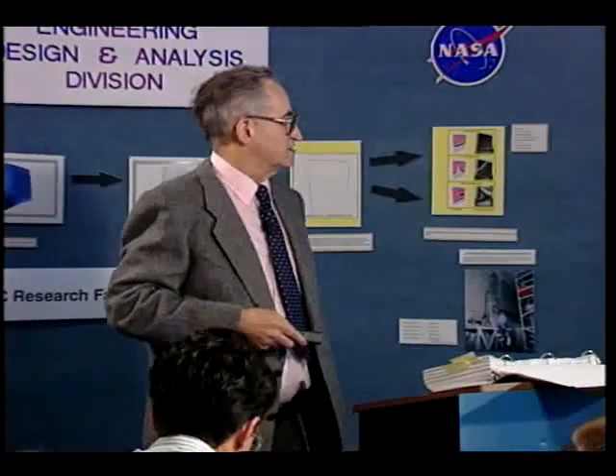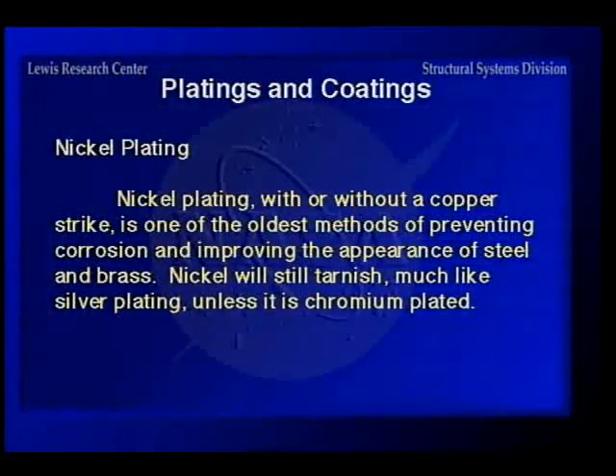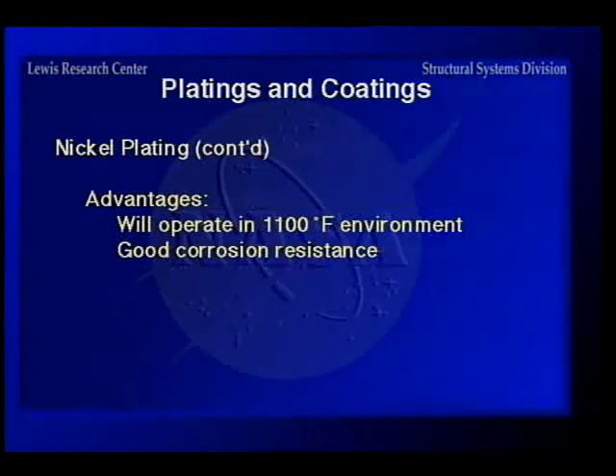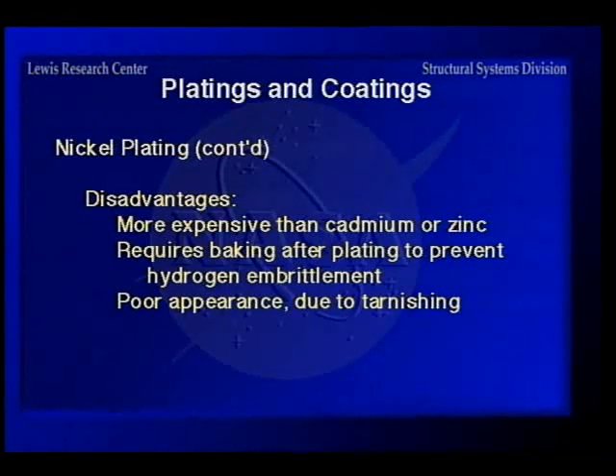Now, nickel plating. Nickel, with or without a copper strike, is one of the oldest methods of preventing corrosion and improving the appearance of steel and brass, but it'll tarnish unless it's chromium plated. But it has a fairly high allowable temperature and good corrosion resistance. The disadvantage, it's more expensive than cadmium or zinc. It requires baking after plating to prevent hydrogen embrittlement, and it doesn't look too good when it starts tarnishing.